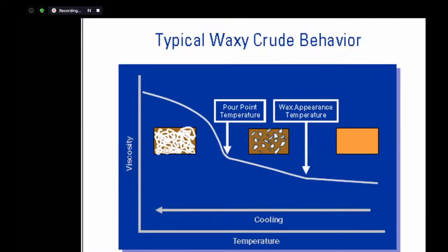Okay. So what happens in this curve is, if you look at the orange part, you could see there are no wax crystals. That doesn't mean, again I am repeating, that paraffin is not present there. Paraffin is a basic constituent of the crude oil. What happens is, when the temperature is decreased, the solubility of the paraffin wax decreases. Now these wax crystals would come out, and on further lowering the temperature, these paraffin waxes agglomerate to each other, come together, entangle themselves and create a blockage for the pipe.